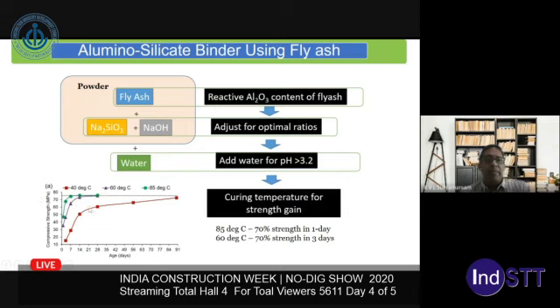And we've also reduced the temperature demand for curing down to 40 degrees Celsius. That is the temperature that is common in summers in India. For about 6 months of the year, the high temperature in most of India exceeds 40 degrees. So we're able to achieve a binder that gives us 80 megapascal strength using fly ash, which is a waste material. And this entire process has been developed by understanding the chemistry of the process.